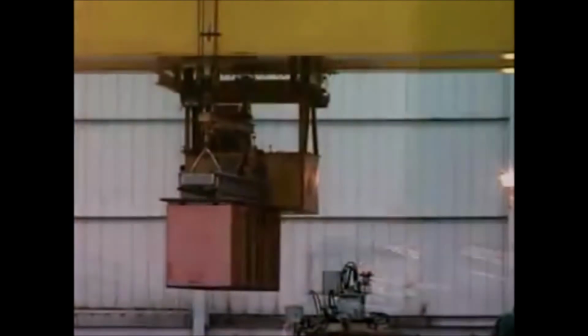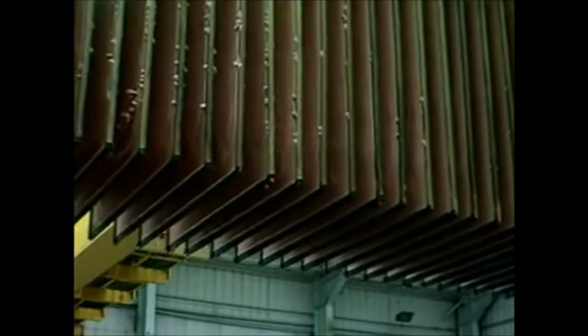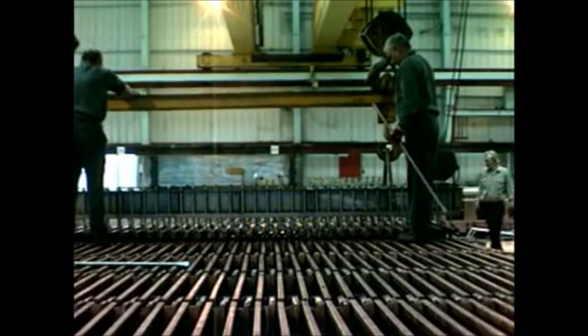Once a week, the cathodes, with a 6 mm thick coating of copper on each side, are removed from the cells. The deposited copper is separated from the cathodes by flexing them and stripping the copper away with knives. The steel cathodes are then reused. Anodes last 3 weeks before being removed. About 12% of the anode remains after this time. These spent anodes are washed to remove further precious metal residues and recycled back into the anode furnace.